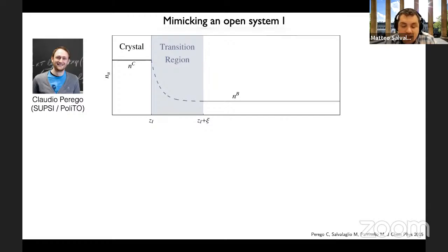And in this case, basically, I would like to discuss what happens when we have a system like a simulation box, which is sketched here, where we have a region of the simulation box that represents a sink, like a crystal, and a solution that provides material to this sink. Now, in a situation like this, in a macroscopic system, we would see that the growth of this crystal, so that this front moves, so it grows under the effect of a concentration that never changes, because typically a crystal is in contact with a reservoir that is much, much larger than the volume that we are able to model